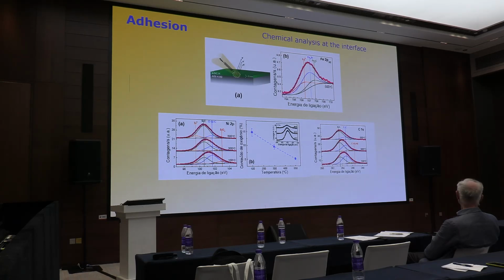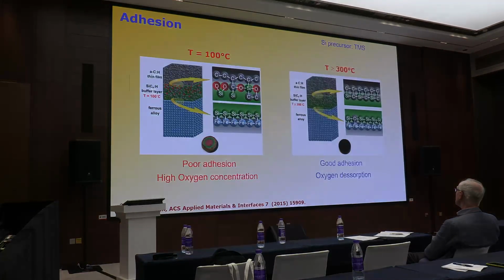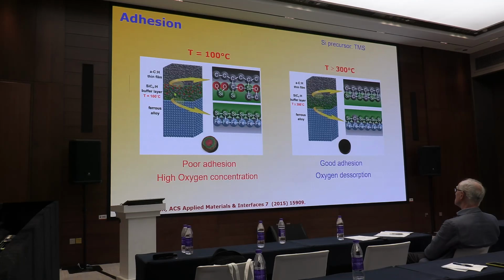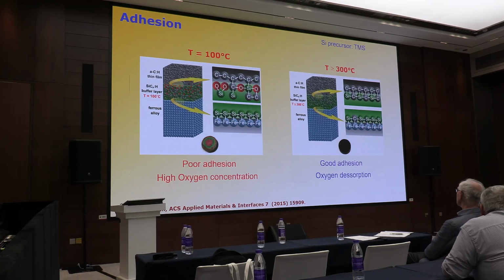Okay, now this is a picture. The poor adhesion is due to high oxygen concentration. Here we have more oxygen, and we have less interaction or less chemical bonding between the carbon thin film and the interlayer made of silicon carbide. But when we remove the oxygen, in this case due to the temperature, we can increase the interaction of carbon and silicon, and the adhesion is better because we have more chemical bonds of silicon and carbon at the interface between the interlayer and the amorphous carbon thin film.